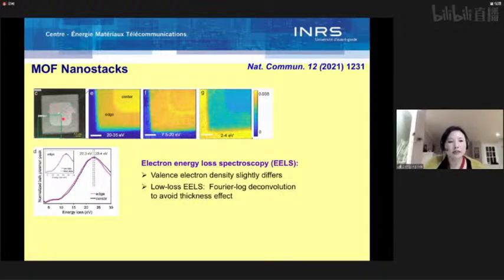And the slight difference between the top plate and the bottom nanoplate was also confirmed by low-loss electron energy loss spectroscopy. We did a low-loss mapping, and we can see that between 20 and 33 there is a slight intensity difference. And if we look at the bulk plasmon peak, you can see the top plate and the bottom plate have a slightly shifted peak position. This indicates that the top plate and the bottom plate have a slightly different valence electron density.